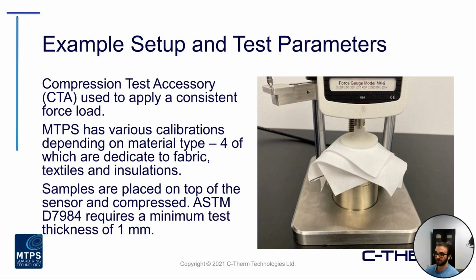As I mentioned, the MTPS has various calibrations depending on the material type that you're working with, and some of which are dedicated specifically to these fabrics, textiles, and insulations. And then ultimately your sample is placed on top of the sensor and compressed. The standard does require a minimum test thickness of 1 millimeter. So in the scenario where you may be dealing with a very thin fabric, there's a layering technique that can be done, somewhat detailed in that picture on the right. But that's just kind of a general example of a setup.